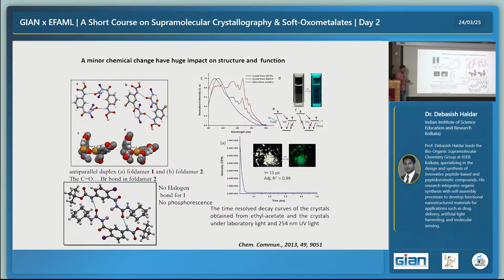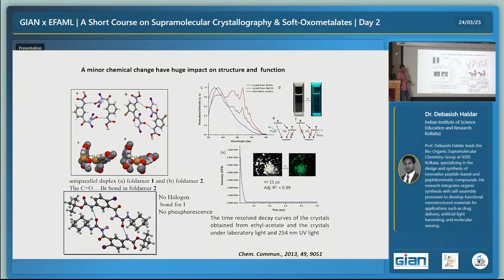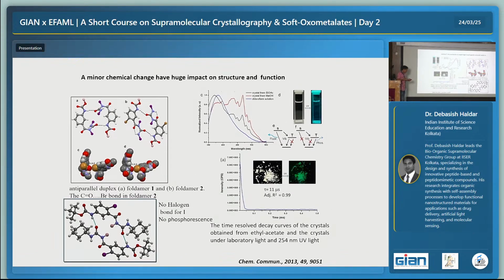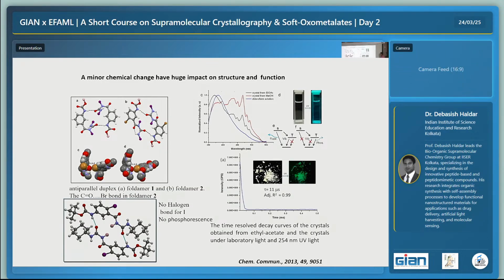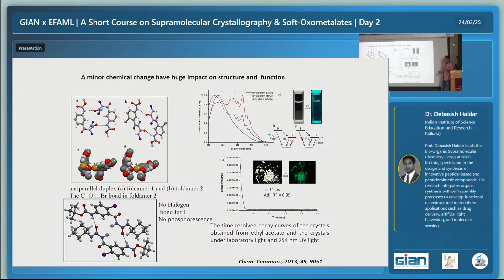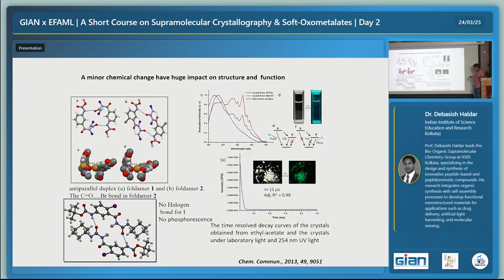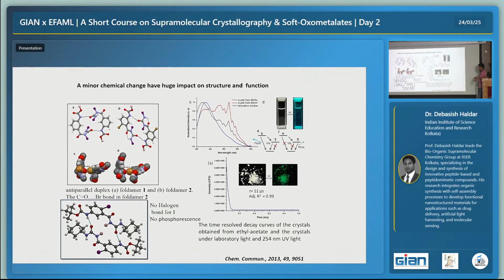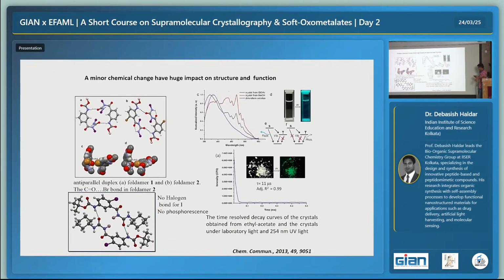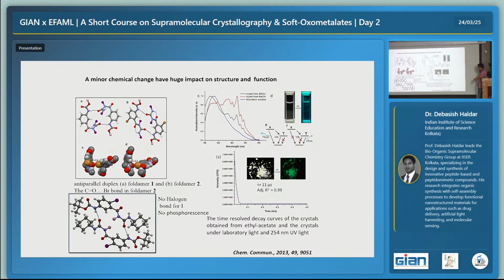And then we thought maybe iodine will have a higher impact, maybe the phosphorescence lifetime will increase, so we replaced the bromine with iodine. But surprisingly, with iodine there is no halogen bond and the compound is not phosphorescent anymore. So this change from proton to bromine to iodine has a huge impact on the structure and function of the compound.